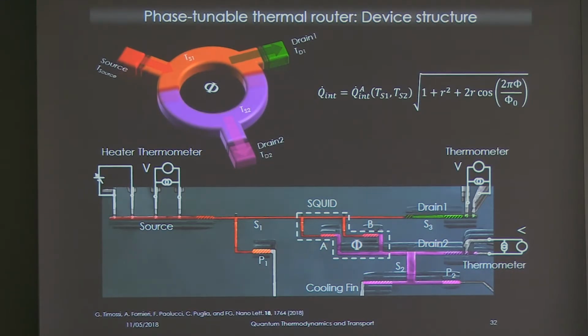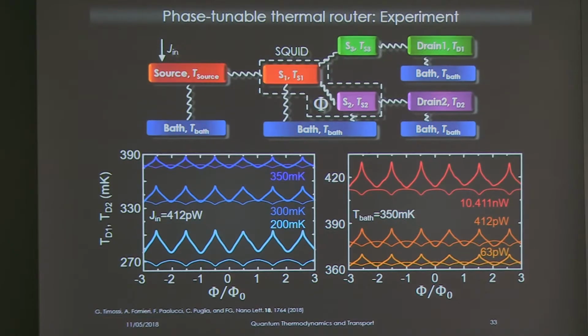What mainly controls the swapping regime is the electron-phonon coupling, so how drain 1 and drain 2 exchange heat with the lattice, whereas the general oscillation is given by the flux. If we look at this kind of system, the thin line is drain 1 and the thick line is drain 2. You see that we start at low temperature with some fixed power as a function of the magnetic field in the interferometer. We see that they fully operate in antiphase. When one is maximum, the other is minimum, as expected, and they fully oscillate.